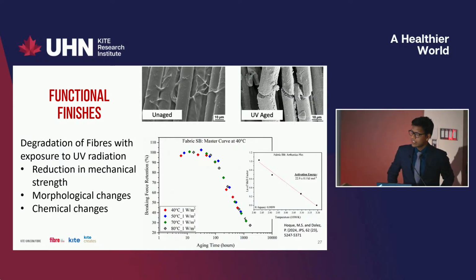And then we evaluated the strength. We evaluated other properties, like chemical degradation, with XRD and with FTIR as well. But here I'm showing the example of strength loss with different temperature and irradiance. The idea here is to show that this study is based on high performance fibers, which are way stronger than the conventional fibers we are using. We found that with light, the fabrics degrade very quickly. It has morphological changes, and it has chemical changes.